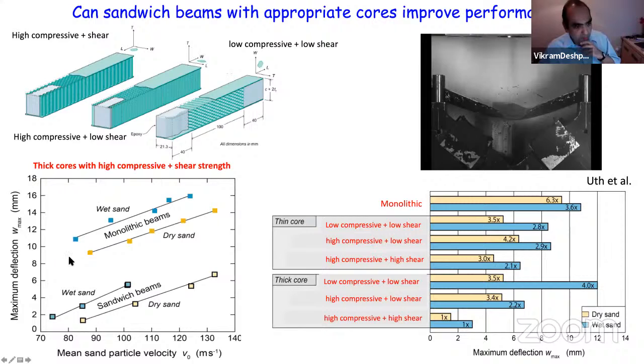And we will then look at the deflection as a function of the sand particle velocity, because remember, everything is perfectly measurable now from these experiments. And we are going to compare against monolithic beams of the same mass as these sandwich beams, and wet sands and dry sands. But now you can see that there's significant reduction in the deflection, right? I mean, factors of 5 or even more, basically, that the sandwich beams are doing significantly better than the monolithic beams. But in this plot here, I've plotted thick cores with high compressive strength and high shear strengths.